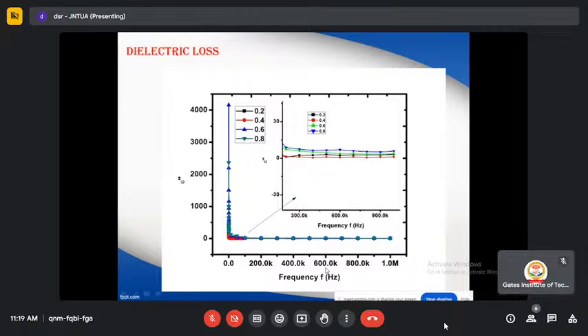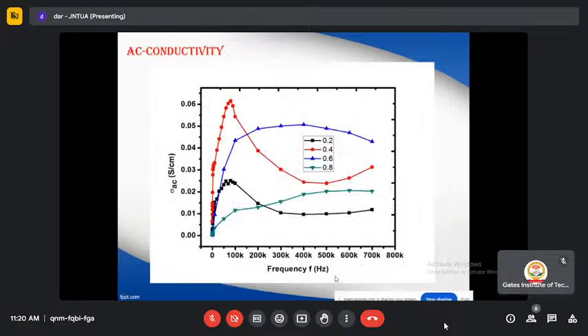So as a whole, we can say that the inhomogeneous dielectric structure is accountable for this behavior of epsilon dash and dielectric loss epsilon double dash with frequency. Large epsilon dash and epsilon double dash values for these two combinations, x equal to 0.6 and 0.8, were recorded in the megahertz frequency range, which may be suitable for dielectric absorber applications at larger frequencies. Now we have also determined the AC conductivity. All these studies were done using an LCR meter, which is available in our laboratory.